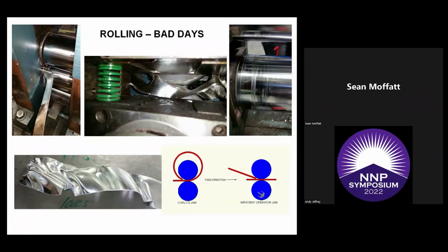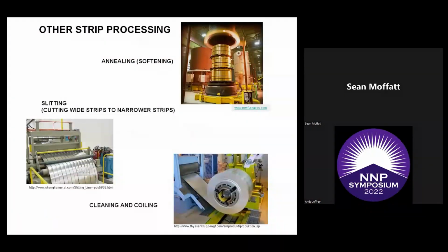So after rolling, we have other strip processing that can be done. We can have annealing if we need to soften the strip, because the rolling of the strip work hardens. We have slitting. Strips are normally produced like 24-inch or 48-inch wide, and if you need it to fit into a die set to make blanks, it only needs a 3-inch wide strip. Well, the strips are slit down to the proper size that you need, and there's also all kinds of cleaning and coiling up that needs to be done with the strips as well.